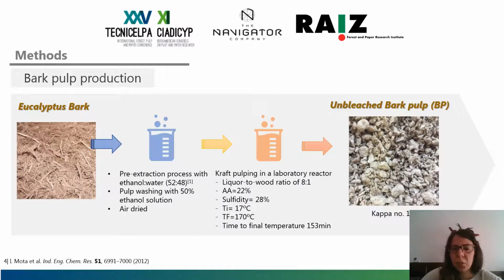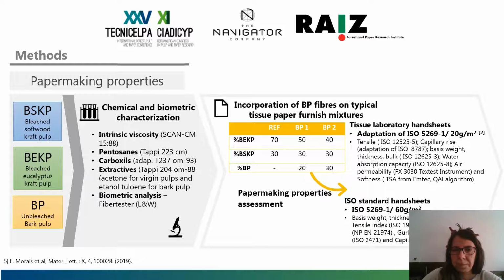For this study, we used eucalyptus bark from a mill, and this bark was initially subjected to a pre-extraction process with a mixture of ethanol and water, and then after this process of extraction, the bark was subjected to kraft pulping in a laboratory reactor, and then the resultant unbleached bark pulp had a kappa number of 13.9. This pulp was then used in the other studies.